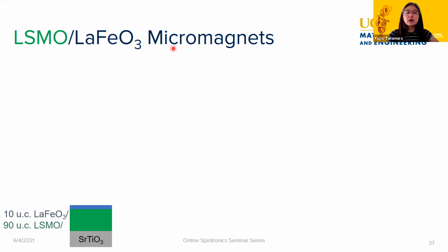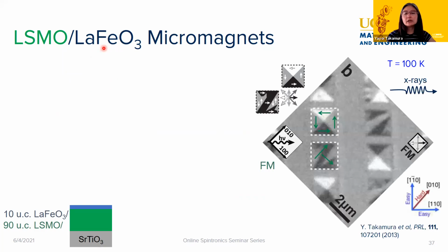In this case with a bilayer structure, we have a fairly thick LSMO layer at 90 unit cells, and 10 unit cells of a ferrite layer, which is just the pure lanthanum iron oxide. If we first look at the ferromagnetic layer, the LSMO layer, we pattern them again in 2 micron squares. What I show you are a couple of different squares, because you can see that they all have different patterns. The one here in the top left is that Landau pattern that we're expecting.